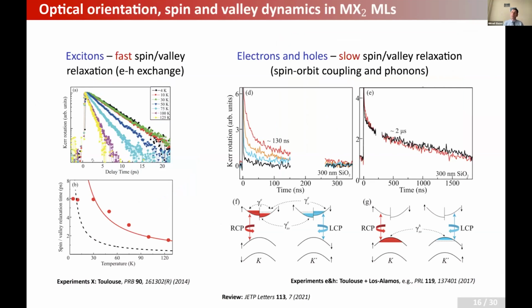You have very fast spin dynamics of excitons, but if you turn to the resident electrons or holes, so if you add doping and study the signals at long times, then electrons and holes show a very slow spin and valley relaxation. It could be on the order of hundreds of nanoseconds in some cases, and in some cases even on the order of microseconds. This is because to lose the polarization, you need to flip the valley and simultaneously the spin, and these processes are very slow. So for excitons, everything is very fast because of the long-range exchange interaction.